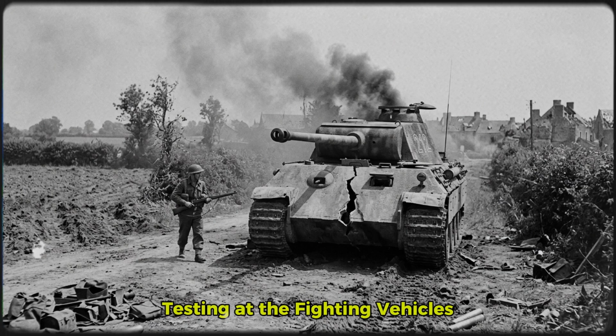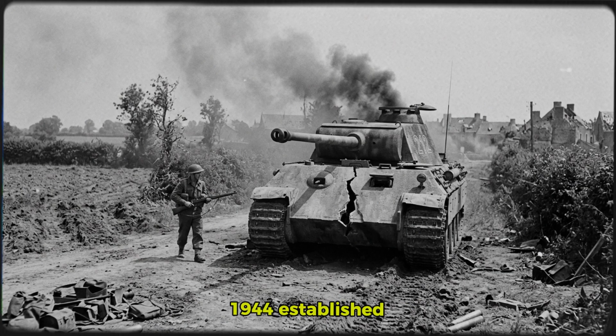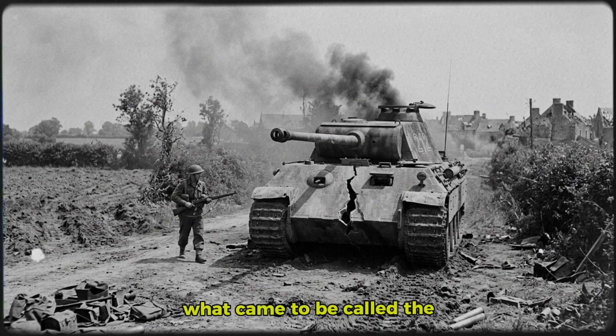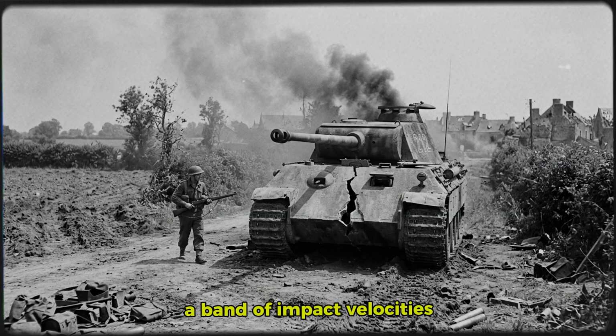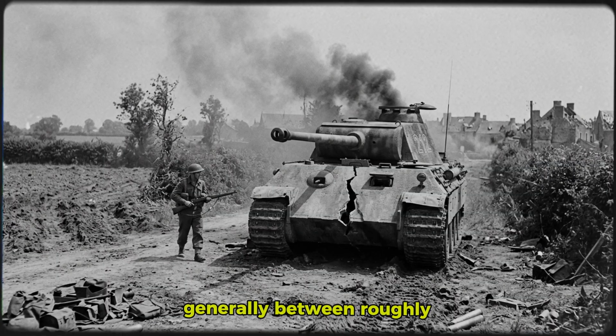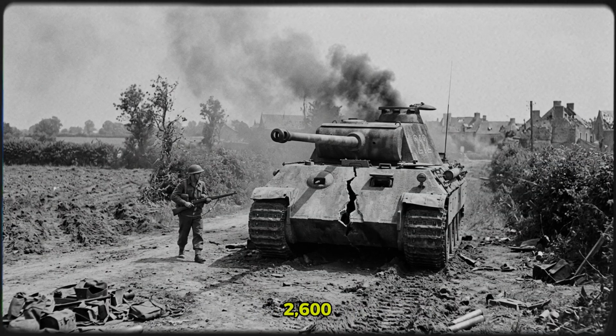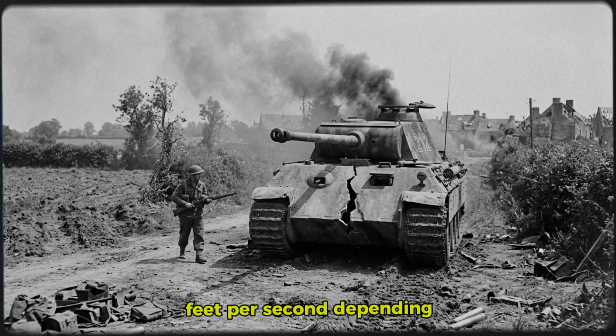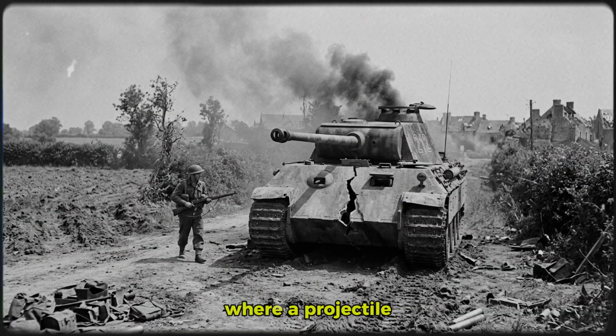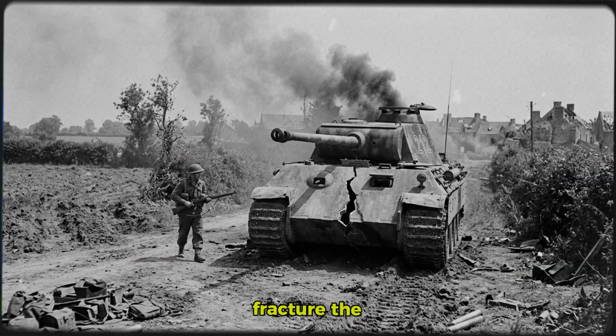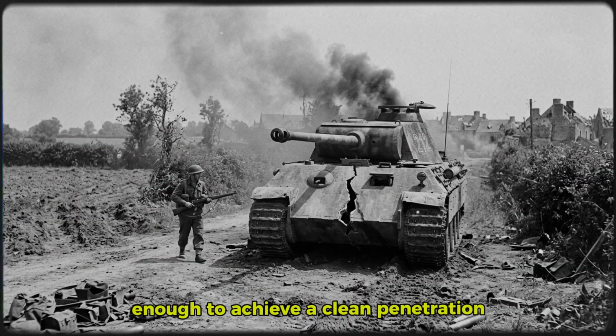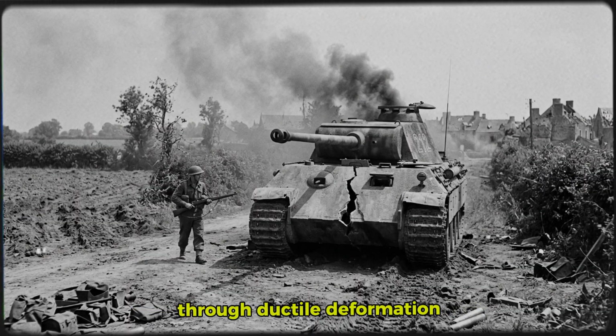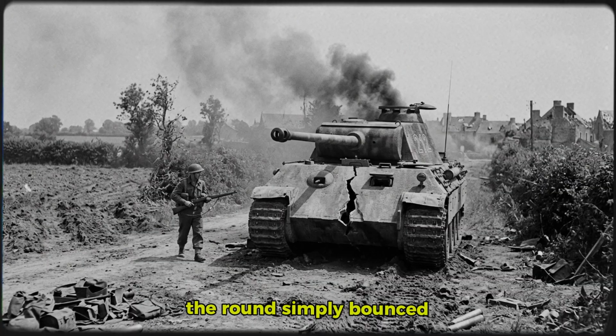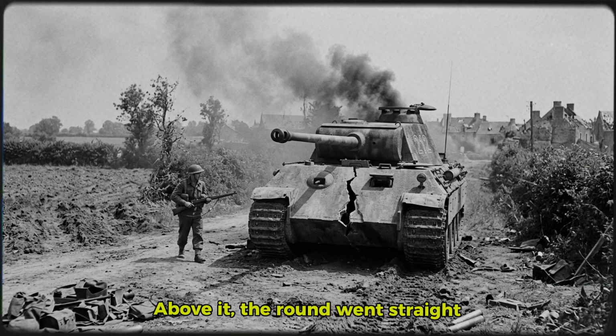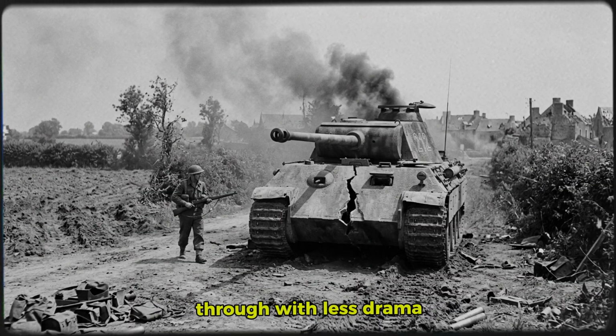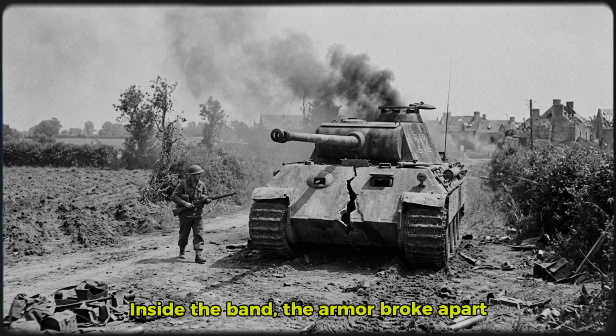Testing at the Fighting Vehicles Proving Establishment through late 1944 established what came to be called the shatter gap, a band of impact velocities, generally between roughly 1,500 and 2,600 feet per second, depending on the specific plate and angle, where a projectile struck with enough energy to fracture the brittle armor, but not enough to achieve a clean penetration through ductile deformation. Below that band, the round simply bounced. Above it, the round went straight through with less drama. Inside the band, the armor broke apart.